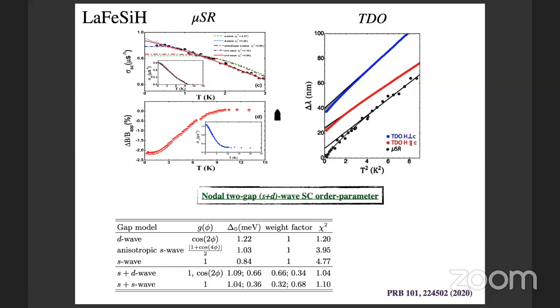So we did a μSR experiment, a transverse field μSR experiment, to determine the superconductor magnetic penetration depth as a function of temperature, especially how the graph looks. The circular data points represent the experimental data, and there are many dotted or solid lines. Those all represent the fits using the D-wave, anisotropic S-wave, isotropic S-wave model, and multi-gap nodal